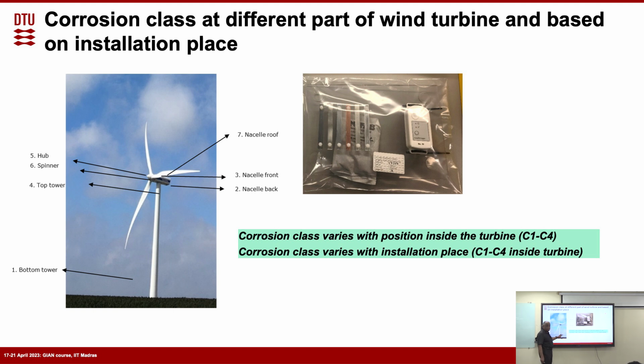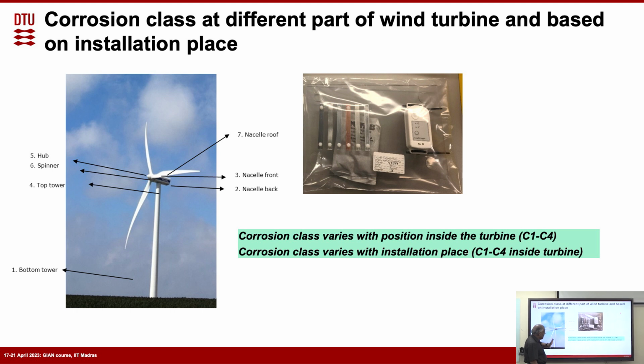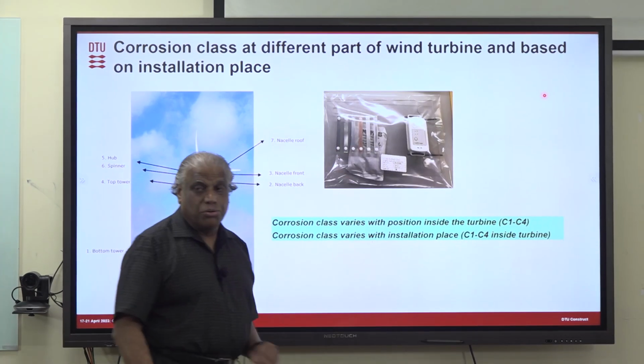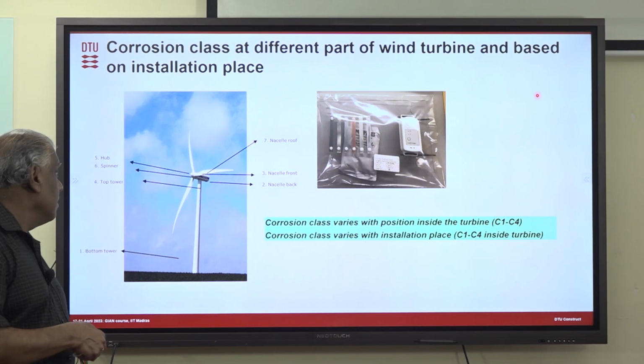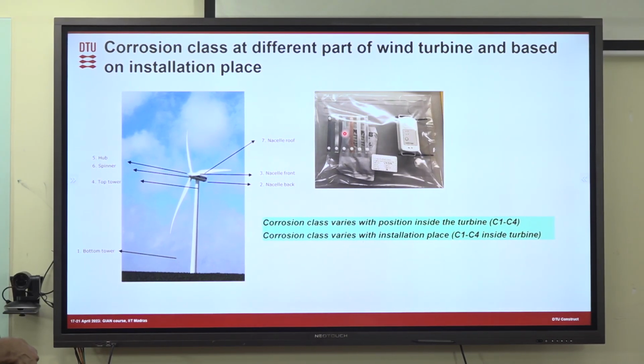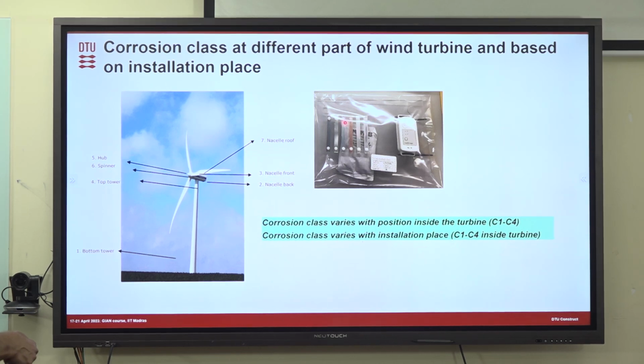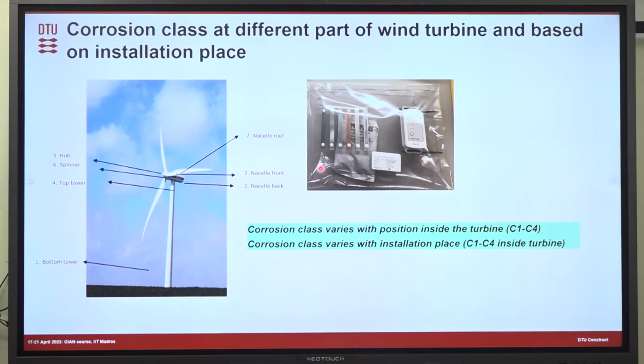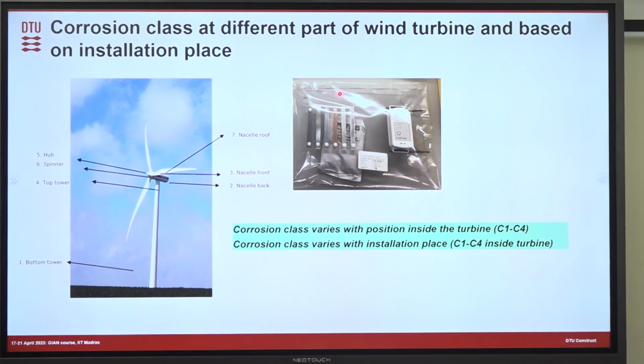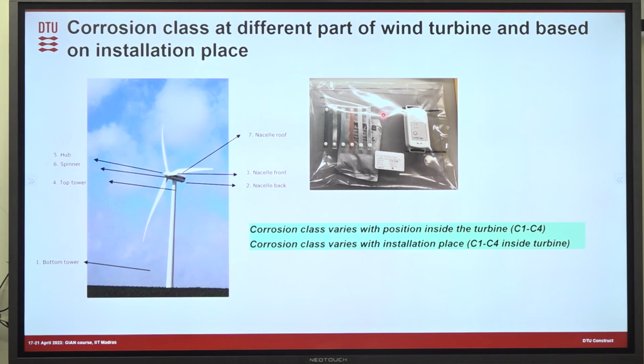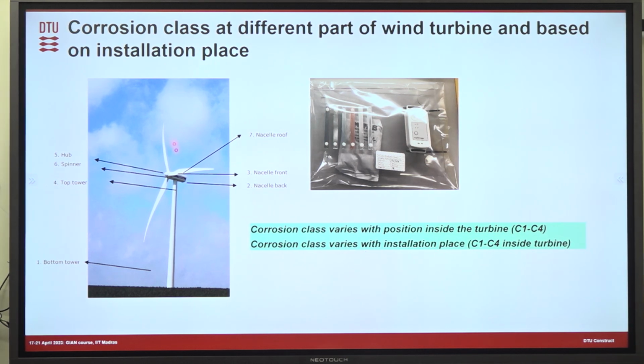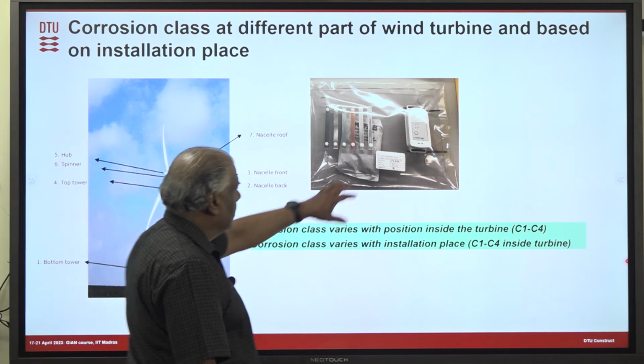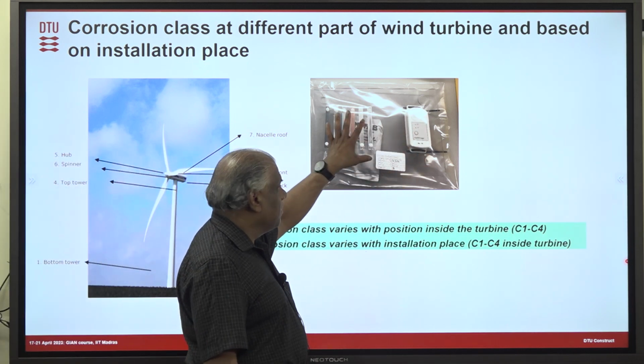We did a study with them, a kind of corrosion analysis. In this particular case, at that time, we used corrosion coupons. We took silver, copper, zinc, aluminum and steel coupons, which is a standard method, and along with a humidity and temperature sensor, we kept them at different parts of this wind turbine for 1 year. After 1 year, we took them out. Within that period, the sensors were collecting the humidity and temperature data, and the coupons were getting corroded.